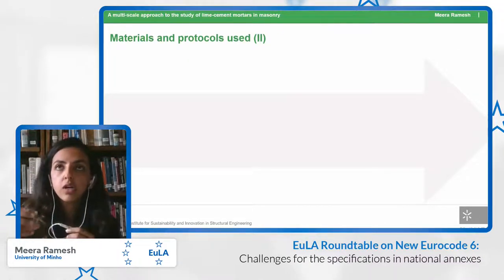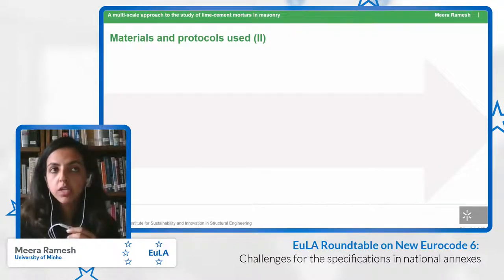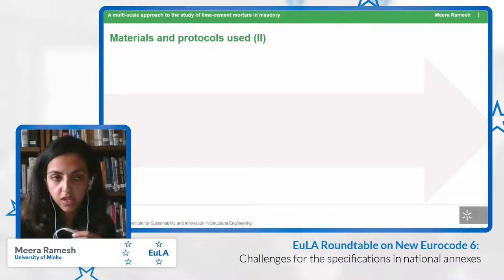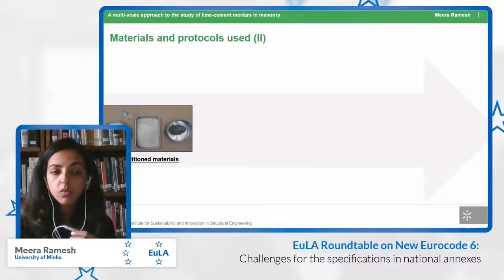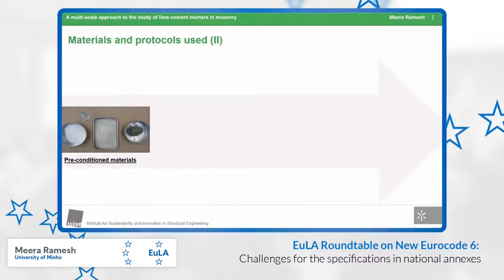For the protocol of actually casting the mortar, we wanted to make sure that the process was robust enough that every time we performed the casting, we would get repeatable results. For this, the first thing that we did was to use preconditioned materials. And what I mean by that is that the lime and the cement were stored at 20 degrees Celsius for at least 7 days prior to every casting. For every casting, the aggregate was heated up to 105 degrees Celsius and cooled down, so there was no influence of extra moisture. And water was stored in the laboratory, where pretty much through the year, the temperature ranged between 25 degrees to 18 degrees, or sometimes going up to 16 degrees, but the water temperature was also stabilized.